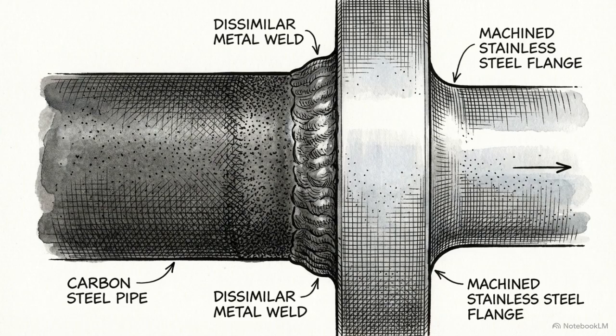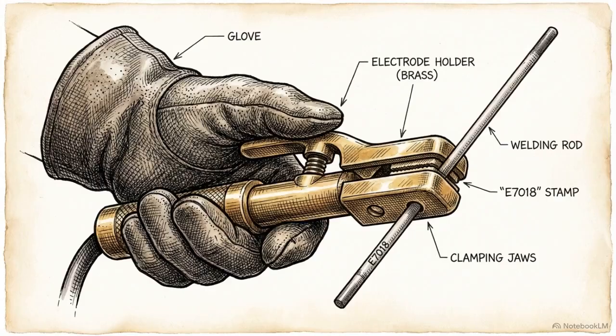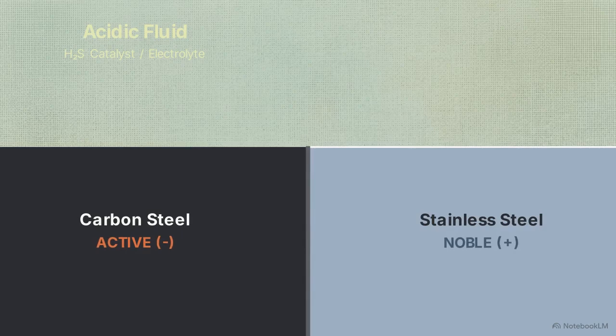The investigation then moves to the joints. The carbon steel pipe has already been fused to the correct stainless steel flanges. This reveals the second fatal flaw. To join them, the welder used standard E7018 carbon steel filler wire. Fusing 2 completely different metals in the presence of an acidic fluid creates a dissimilar metal joint. It functions exactly like a battery.